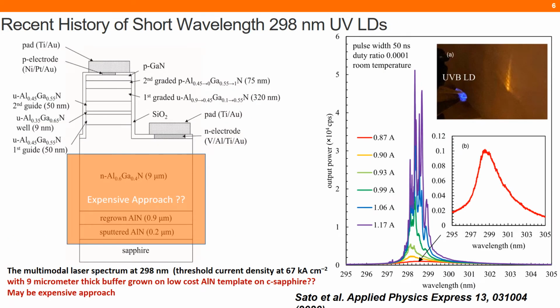Also, Professor Iwaya's group at Meijo University, Nagoya, demonstrated a UVB laser diode at an emission wavelength of 298 nanometers. But this device was grown on sapphire. They first introduced sputtered aluminum nitride, then regrown aluminum nitride, and next grew a 9 micrometer, quite thick, AlGaN cladding layer, and these approaches seem to be expensive.